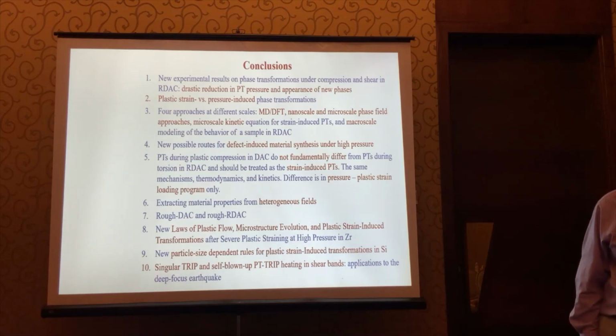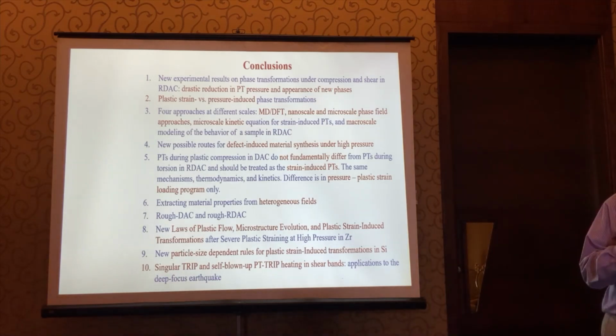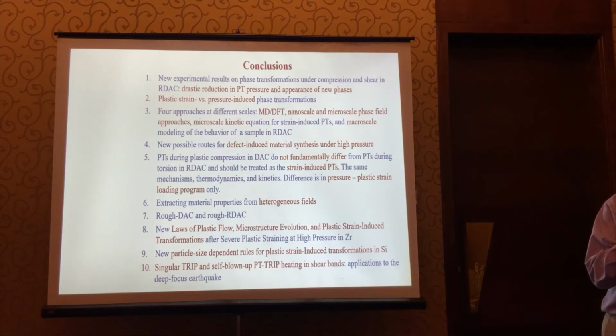Something I didn't get actually. Do you see the grain size effect, let's say, if you use plastic deformation and phase transformation? If you start with a single crystal, do you obtain the same results? No, not at all. We need grain boundaries to produce dislocation pileup. In single crystal, we don't have it, right? So this effect will be absent.